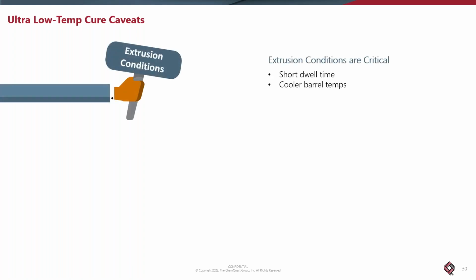When we're talking about low temperature cure, as a formulator, as a chemist, as a material scientist, it's fun to develop these things in the laboratory and to do application studies under lab conditions, but introducing it out to the real world, it brings some hurdles that have to be overcome. Extrusion conditions are critical. You've got to be careful you don't put too much heat, too much energy, too much shear into these systems during the powder production. So you may have to redesign your extruder somewhat to provide a short dwell time and also lower temperature, so you don't get advancement during the extrusion process.